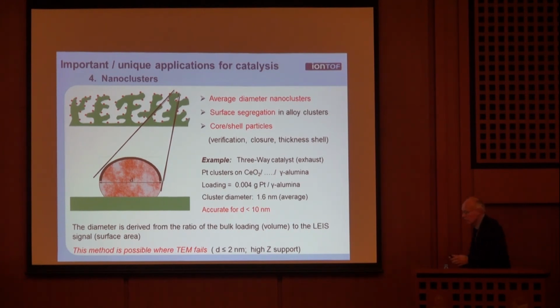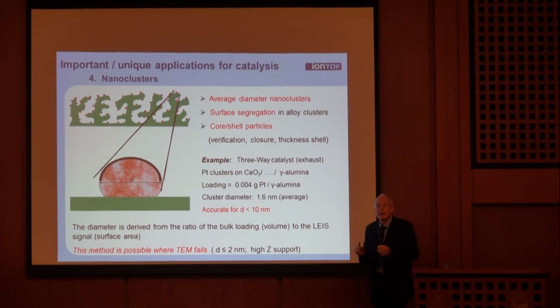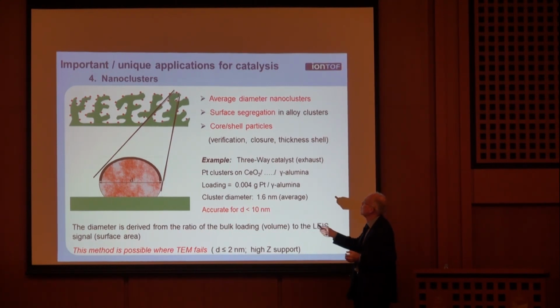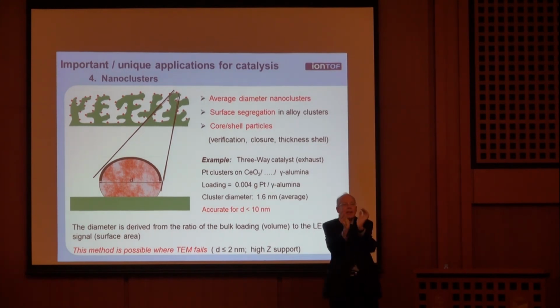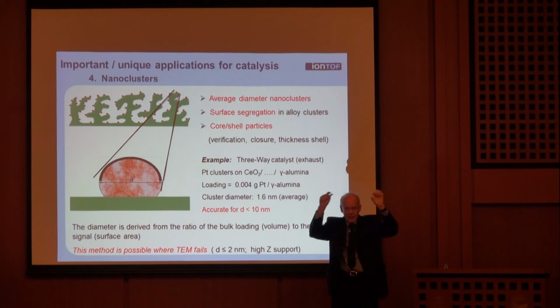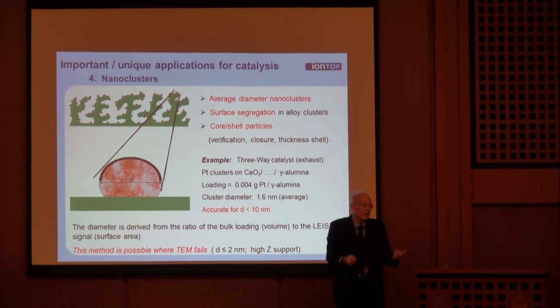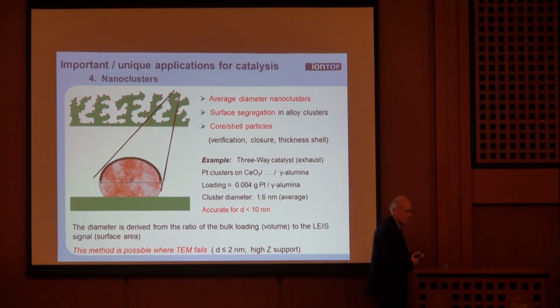And of course, what we do is not only platinum, it's of course real fun to do core shell particles where you have, say, a few nanometer particle where the outside differs from the inside. And so you can determine, is it a real closed shell? How thick is that shell? And so we help to develop new catalysts.